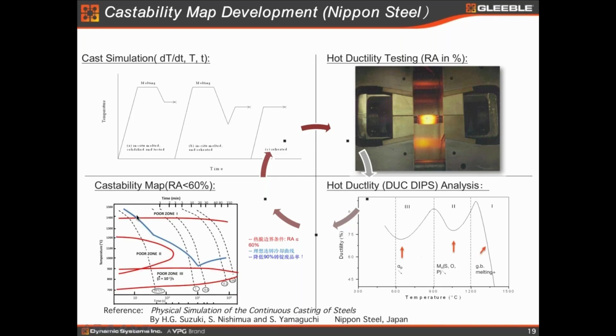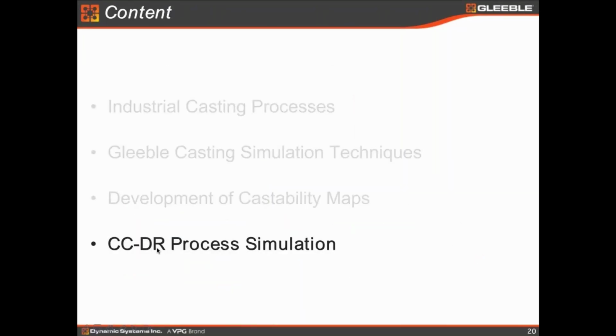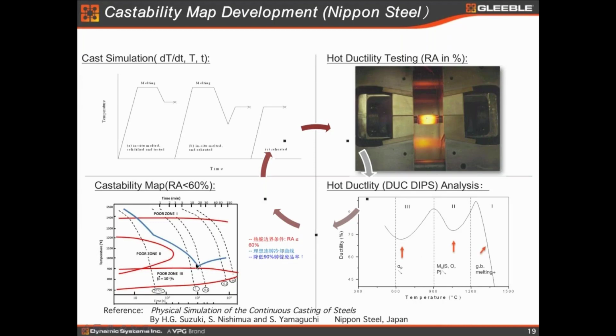They developed this. So instead of cooling that fast, they slow down the cooling in their secondary cooling region. When the billet is getting into almost 1200, 1100 degrees C, they reduce the cooling rate again, so it's not going to get into this poor ductility region. Then when the surface temperature of the slab goes down to around 900 degrees C, before it goes to the third low ductility region from 600 to 900, as you can see from here, they simply stop cooling. Then the surface temperature will rebound because the inside temperature is still hotter, right? This way they let the slab avoid the low ductility regions 2 and 3, and they minimize the thermal or mechanical stress in region 1.